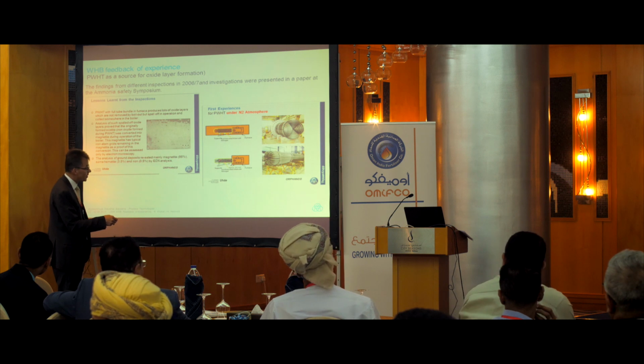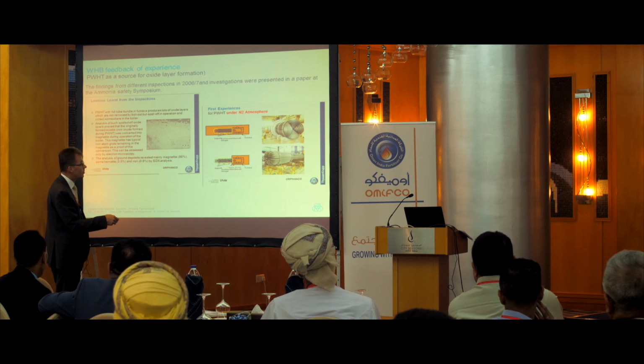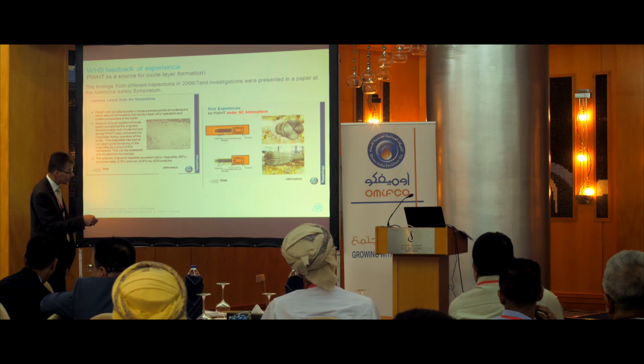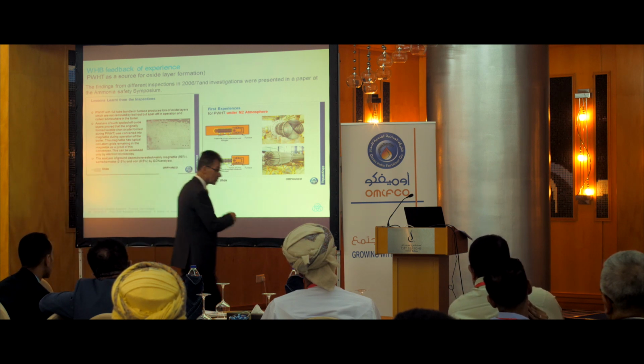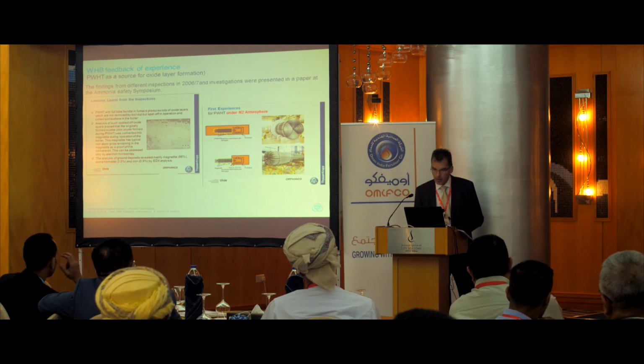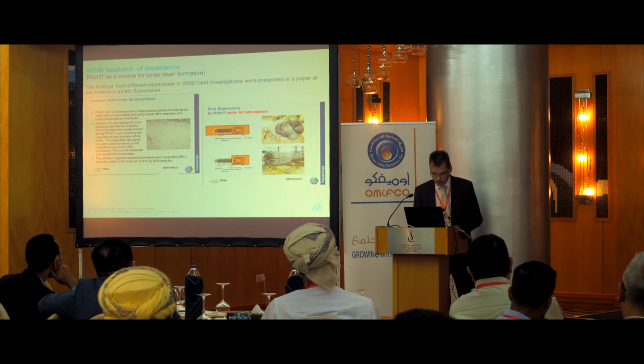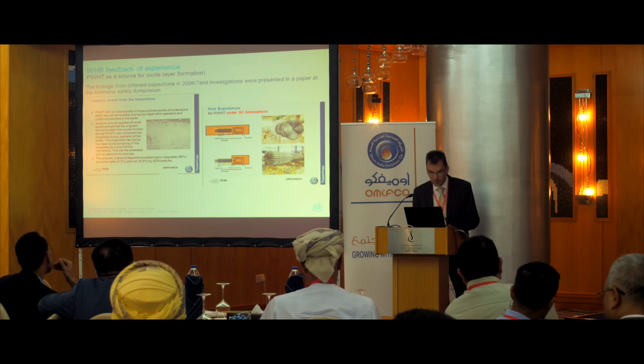This was done, and we have been able to feed in now nitrogen to blanket the whole tube bundle and to avoid any oxidation, any build up of oxide layers. Typical examples you can see here and here. These are very clean tube bundles after the first test of this new kind of nitrogen feeding in this auxiliary shell. All these results of the different investigations and inspections were presented in a paper published 2008 during the Ammonia Safety Symposium. Also no secrets, all things which have been published.